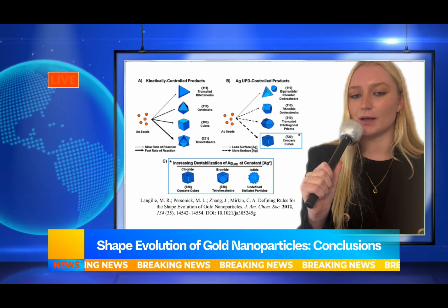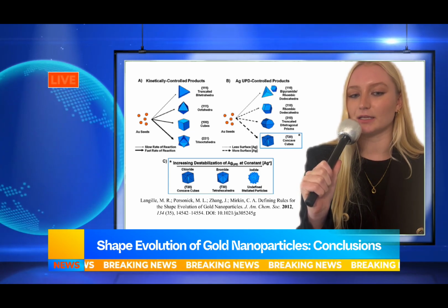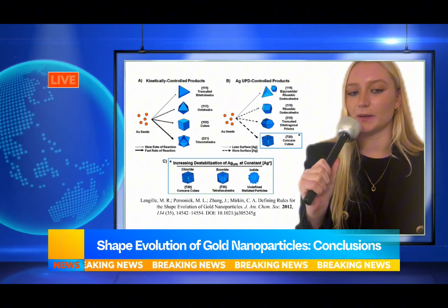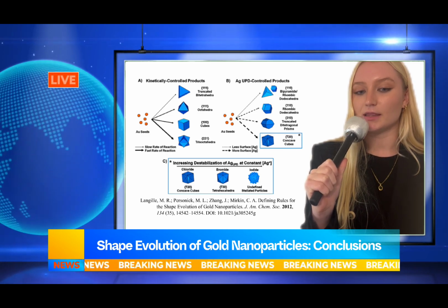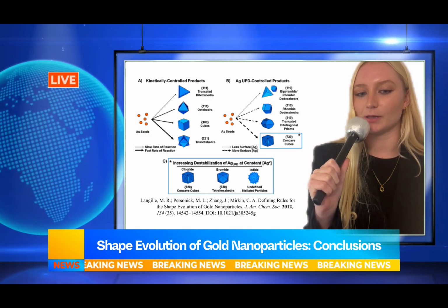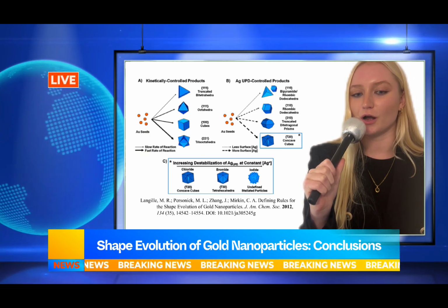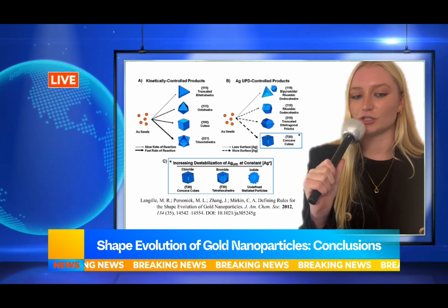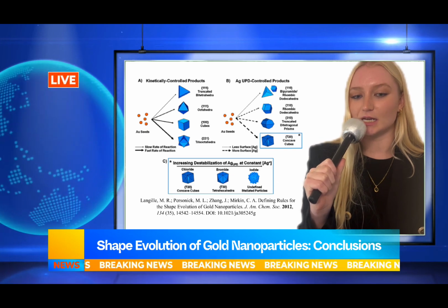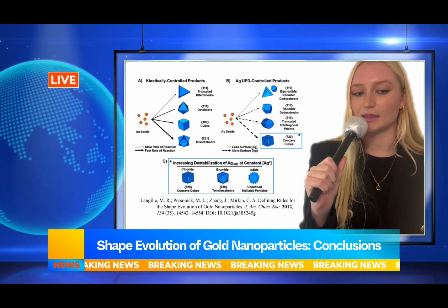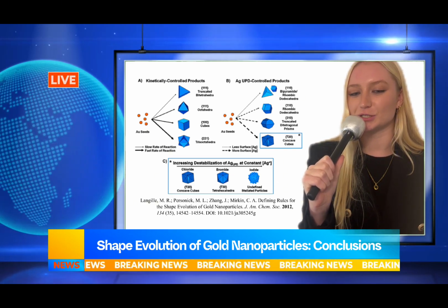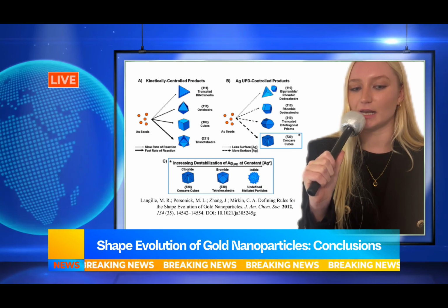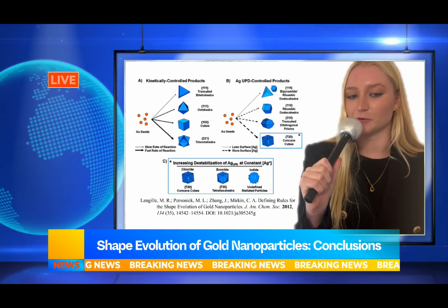Fourth, adding trace amounts of halides either stabilizes or destabilizes the underpotential deposition layer, depending on the size of the halide, meaning that higher energy surface facets can be stabilized with less silver when the silver underpotential deposition layer is destabilized. Fifth, high concentrations of larger halides hinder silver deposition, limiting accessible morphologies. Lastly, kinetic trapping due to the underpotential deposition layer and chloride surfactant enables access to a broader range of morphologies.